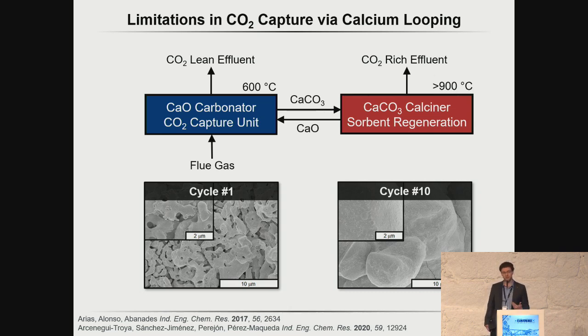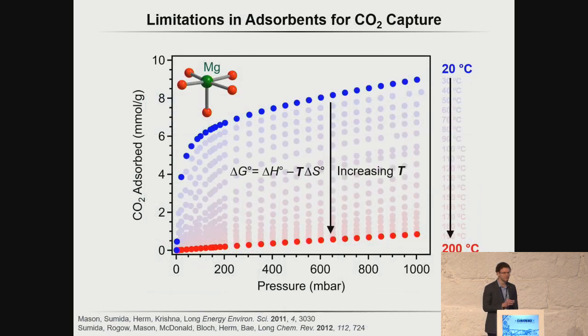Now, one of the challenges here is that sintering is a direct consequence of the large volumetric changes between the oxide and the carbonates. Excitingly, when we think about porous materials, such as metal organic frameworks, we may be thinking about single-digit percent changes in the overall volumetric expansions, which can help avoid some of these sintering problems. Unfortunately, the majority of metal organic frameworks operate through physisorption.